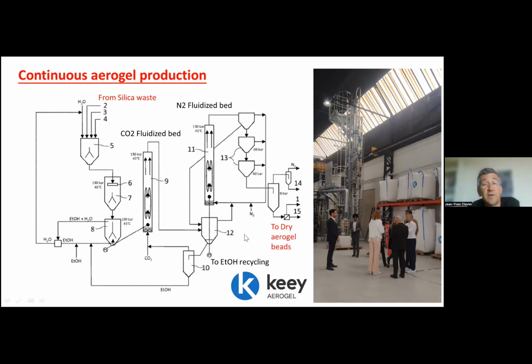And we have recycling. I can't show all the recycling here that have been developed later, but basically we are recycling CO2 here, we are recycling nitrogen, and we are recycling ethanol in a different loop. So every solvent is recycled. We have a fully continuous process, a way to optimize each step independently. And after about 10 years of development, we are launching at the moment the first production batch of these beads of dried aerogel to be used in insulation material. So I will leave Pavel introducing further the concept, but I am of course open to questions.